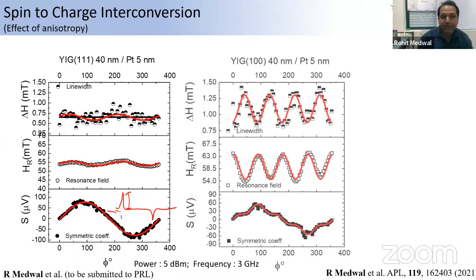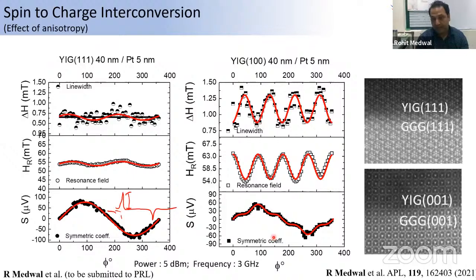But when we do these measurements on the YIG 100, we clearly observe that the sine theta is modulated into sine theta plus a 4-fold symmetry in the ISHE voltage. That is clearly dominated by the resonance field HR plus the anisotropy field, or you can say the delta H linewidth in the ferromagnetic resonance spectra. This was quite resembling, all perfectly in order. We were able to clearly distinguish these two effects and try to deconvolute them, which I will show in the next slide. But I would like to highlight that for YIG 111 there is no cubic anisotropy, and we have a perfect sine theta behavior, whereas for YIG 001 we have sine theta plus the 4-fold anisotropy modulation in the symmetric component of the ISHE voltage.